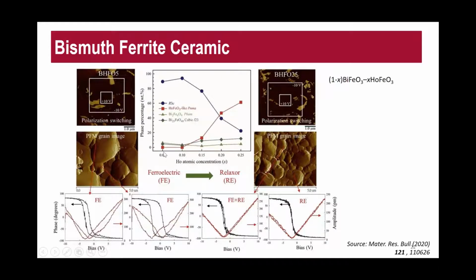And for this, another example is bismuth ferrite with holmium, and we use this to study the phase transition or phase structure of different compositions of holmium. What we found is that it is able to change from ferroelectric to relaxor based on the step-by-step changes in measurements for both materials. So we can see that 25% holmium doped into BFO will have a combination of relaxor behavior in the materials, whereas with only 5% holmium, we have a pure ferroelectric behavior in the materials. And this is again combined with an XRD study to obtain the phase percentage change and be able to correlate well with our PFM tool.